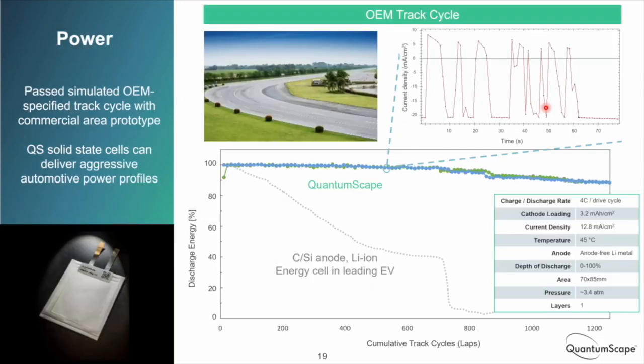So then we put the separators back into a cell and ran what I think is really the most stressful test that I've seen done on our cells. This is a track cycle that we got from our automotive customers. To just describe this track cycle for a minute, this is showing one lap around the simulated track. Just to be clear, our batteries weren't actually in cars driving around the track. We just took this drive cycle and did it on our single layer pouch cells. So this shows current density over time of one lap around the track, accelerations of 4 or 5 C here, and regenerative braking of 1 or 2 C, repeating this very aggressive acceleration on the straightaway, braking going into the turns, and repeating around one lap of the track.